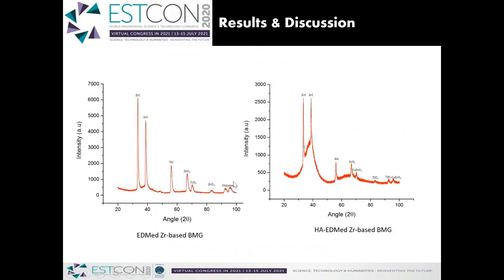And this is the XRD pattern of the EDM'd material, zirconium-based BMG. As you can see, there are so many sharp peaks of zirconium-based carbide, and some peaks of titanium carbide, as well as zirconium oxide. The carbide might be a result of reaction between the zirconium in the workpiece and carbon in the hydrocarbon-based dielectric fluid, respectively. While the oxide might be due to reaction of zirconium in the workpiece material and oxygen, which might be due to flame, which occurred due to heating and melting during the process.